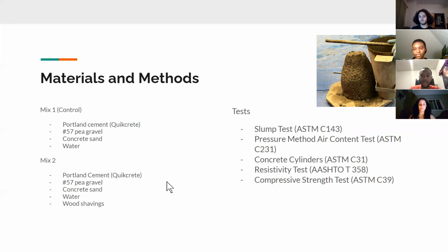After gathering all the ingredients, we mixed them together until we had a homogeneous mix. And then we performed the slump test, which looks at the workability of the mix. And we performed the pressure method air content test, which looks at the entrained air in the mix. Both mixes were then put into 3 4x8 cylinder molds to set and cure for a total of 7 days. After retrieving the cylinders, we performed the last two tests, the resistivity test, which looks at the durability of concrete with respect to corrosion, and the compressive strength test, which looks at the overall strength of the concrete.